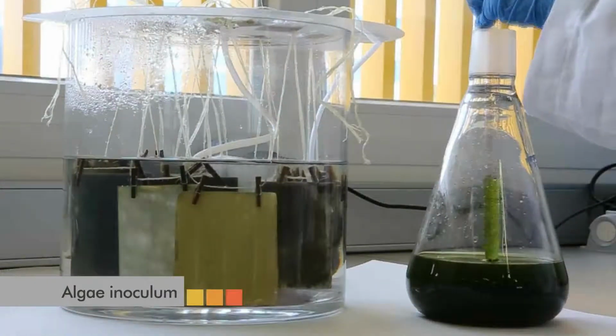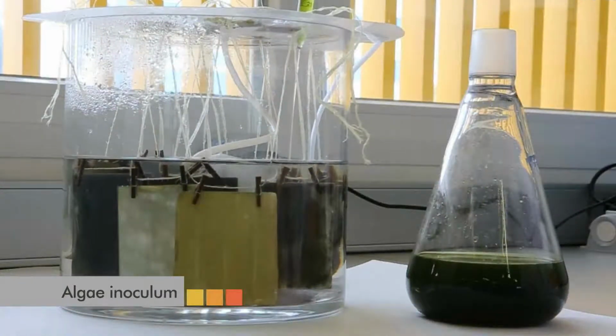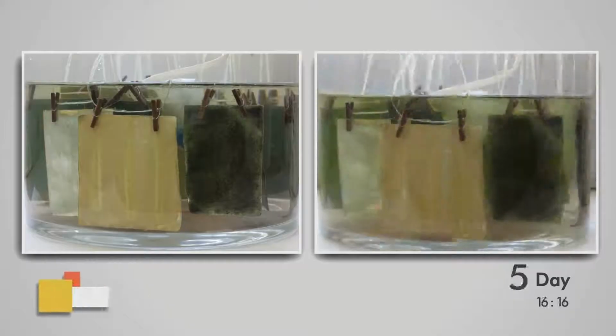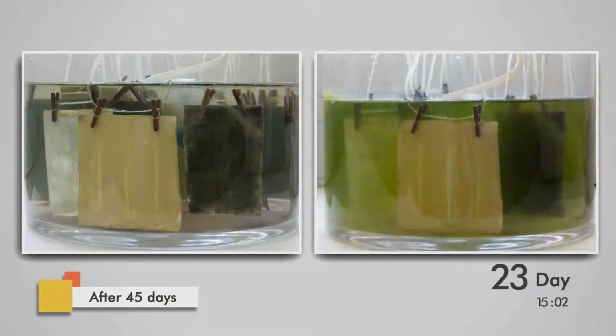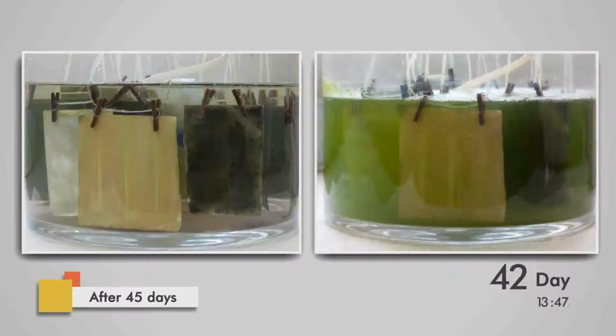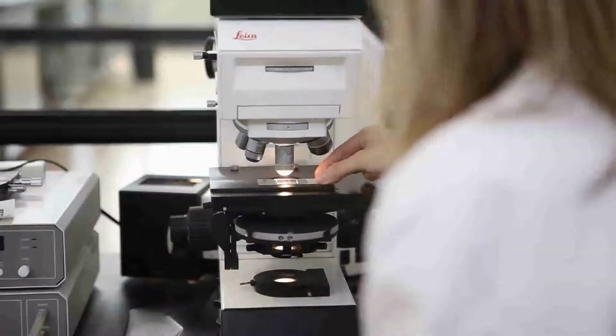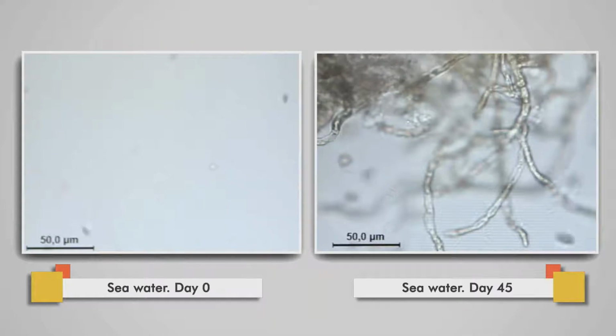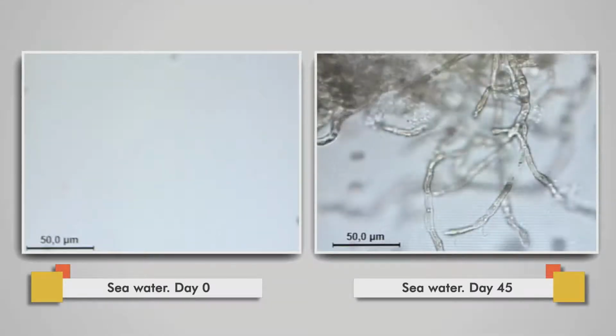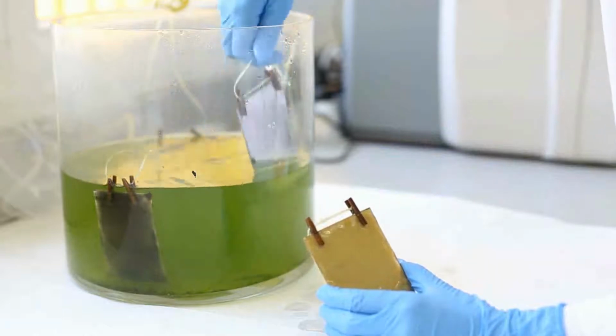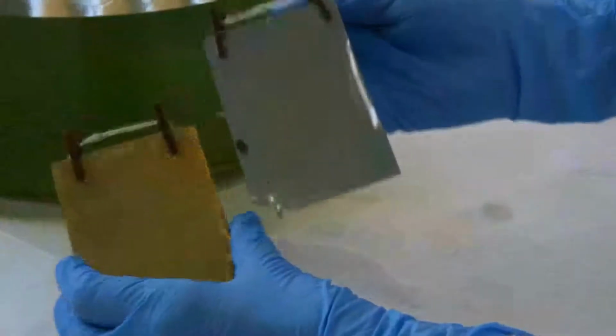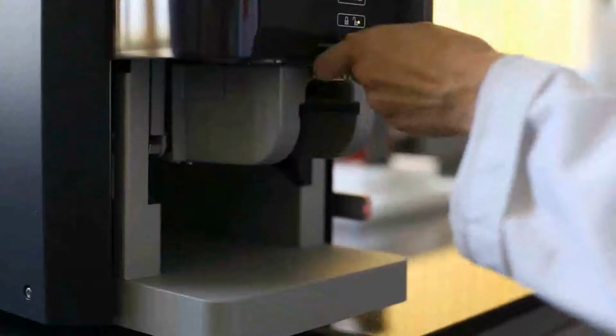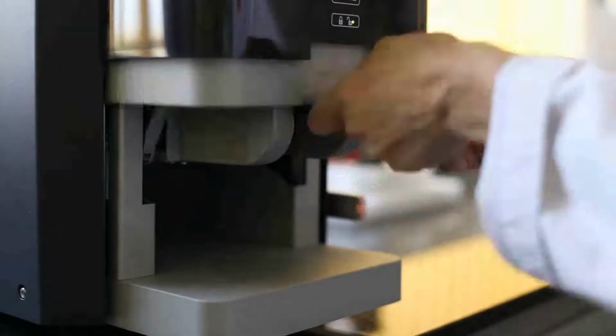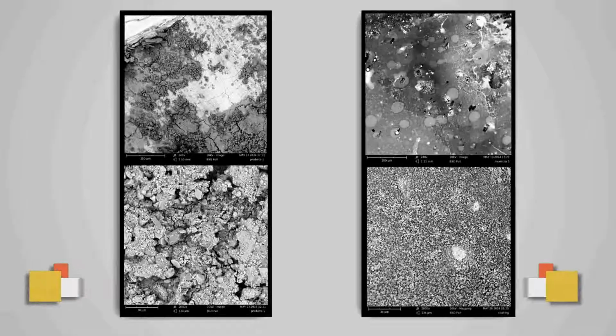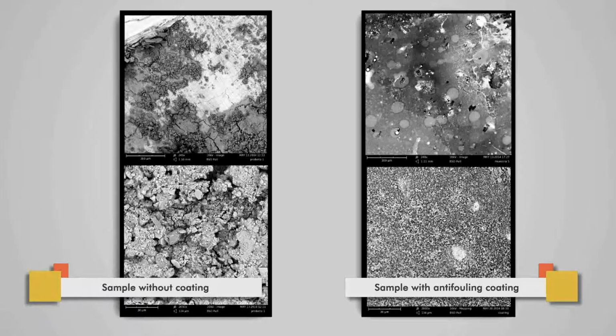With the objective of testing coatings under real environments, they were exposed to seawater with a microalgae inoculum. After a period of 45 days under controlled conditions of temperature, light intensity and nutrients, it's possible to detect by a microscopy analysis an algae and several microorganism growth in the testing water. When comparing surfaces, it's possible to distinguish the presence of algae deposits in the sample without coating. An electronic microscopy analysis shows how the developed formulation avoids the presence of algae and salts generation, characteristic of fouling, ensuring a higher durability of the material.